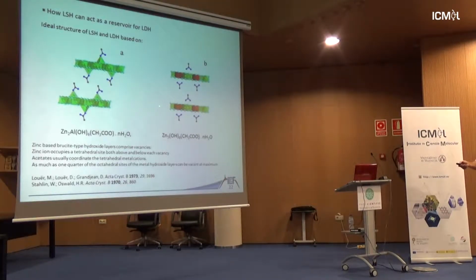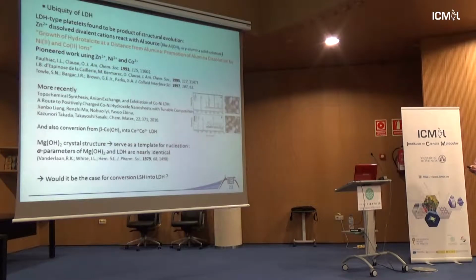Zinc, aluminium is here, and you have aluminium and zinc inside octahedra, only octahedra, and you have no vacancy. Here it's only zinc, and here zinc and aluminium. So that's the main difference: vacancy, no vacancy, tetrahedra, octahedra, and so on. And you will see that with different transition metals it makes sense, because you may have a change of color because you change coordination, and that's a fingerprint that we have been using to address the difference.